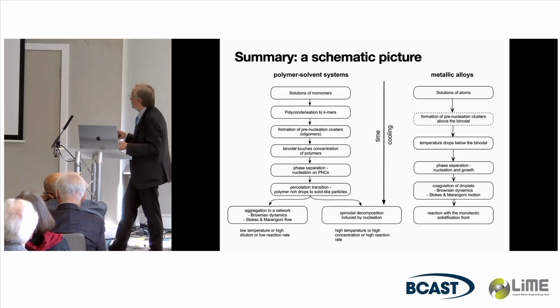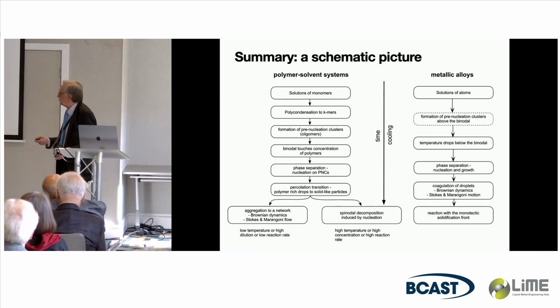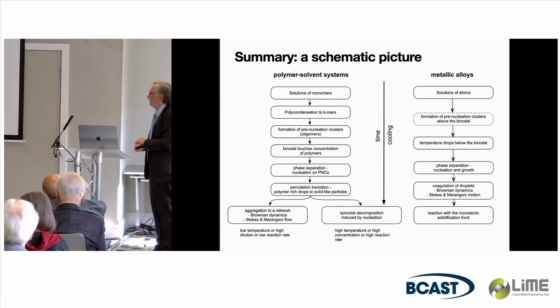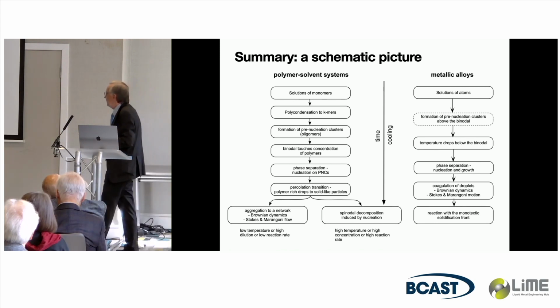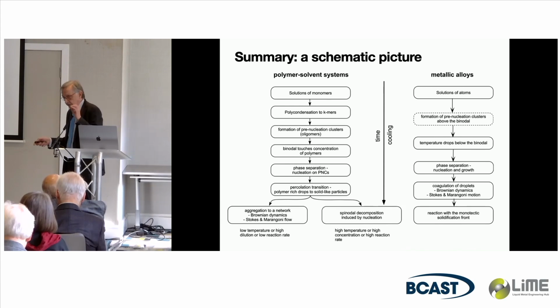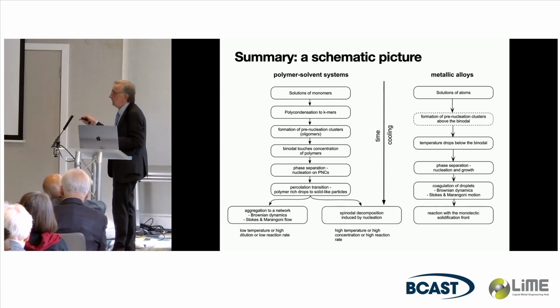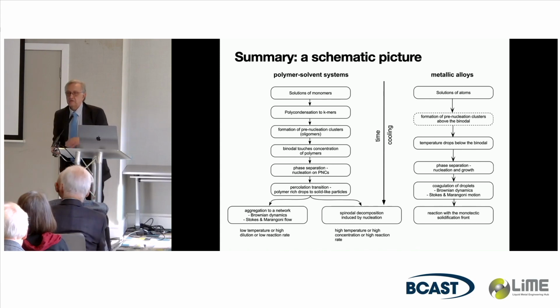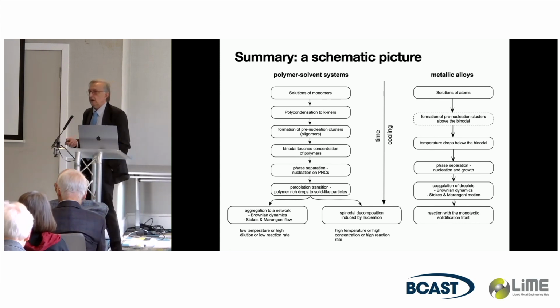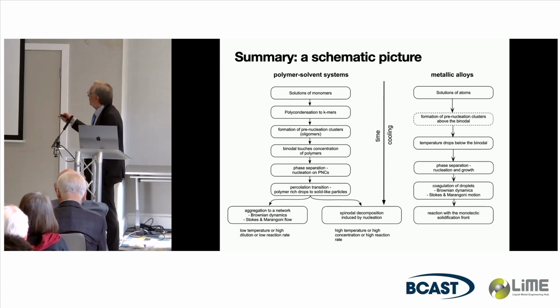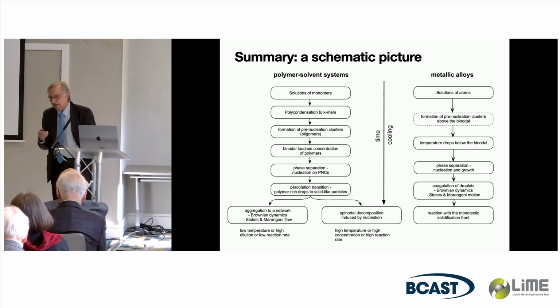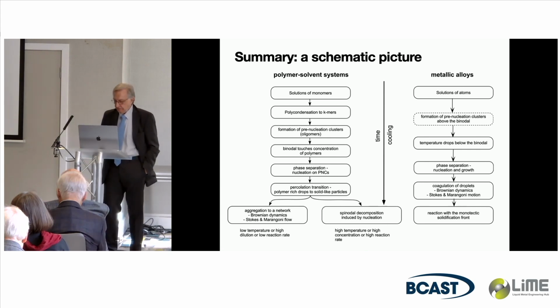When the temperature drops below the binodal, you have a phase separation by nucleation and growth, and of course coagulation of drops by Brownian dynamics, Stokes and Marangoni motion. And of course you have to include the reaction with a monotectic reaction. This is a point which was forgotten in the literature for more than 20 years, that Ferdinand Sommer and Heuer in Chemnitz observed from X-ray scattering and viscosity measurement data that there might be, even a few degrees above the binodal, already clusters of the second phase. So this would then explain why it's not homogeneous nucleation. But it was not followed on.